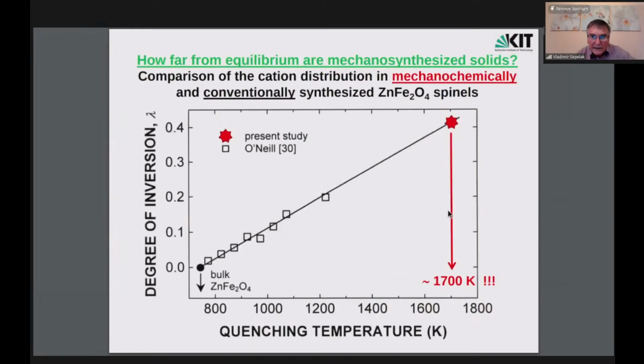And if we look at the degree of inversion in this mechanosynthesized material, 0.41, it corresponds to the degree of inversion of a conventionally prepared bulk material which is quenched from 1700 K. That indicates how far from equilibrium mechanosynthesized zinc ferrite is. The second example is also on the characterization of mechanosynthesized nanospinels, which are in para- and diamagnetic state, using spectroscopic methods.